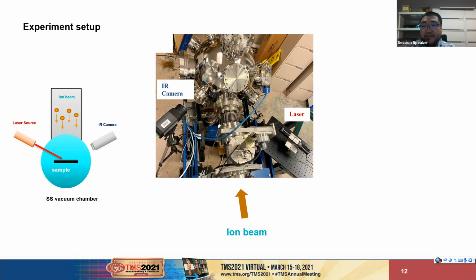And this shows the setup of our in-situ thermal property measurement system, showing the location of our camera, laser, and the chamber which contains the sample stage inside. As you can see, when the ion beam radiation is being performed, on one side the laser source is going to shoot the laser and focus it on the surface of the sample. And the angle between the laser and the ion beam is around 45 degrees. And on the other side, the IR camera is going to capture the temperature information from the surface of the sample in a symmetric way.